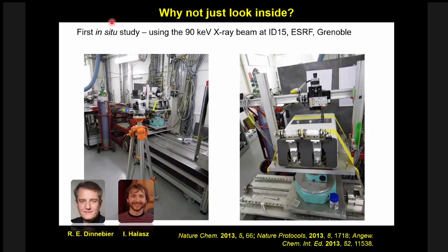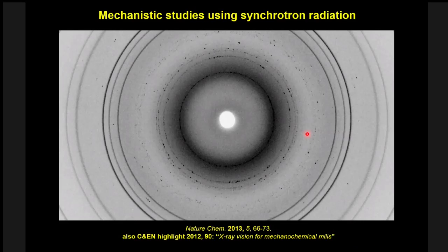Now also we are not quite sure, but we got exciting new tools. One of them is we actually managed to find out that you can take your ball milling device. Here is a ball mill, and you stick it in the path of a really high energy X-ray beam, for example, at the European Synchrotron Radiation Facility in Grenoble, or more often these days in the German synchrotron facility, DESY, and you shoot X-rays straight through the ball mill reactor, through the jar, as it's shaking about, and you record movies that look like this.